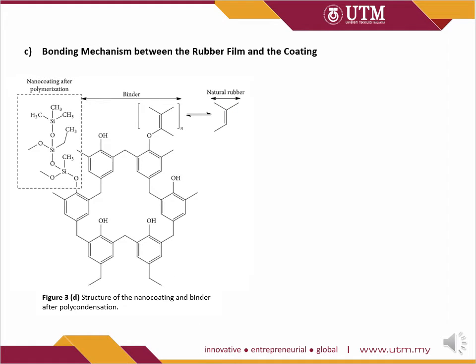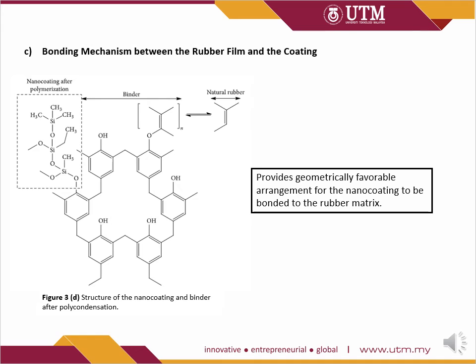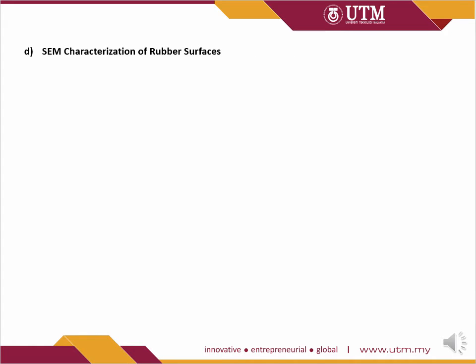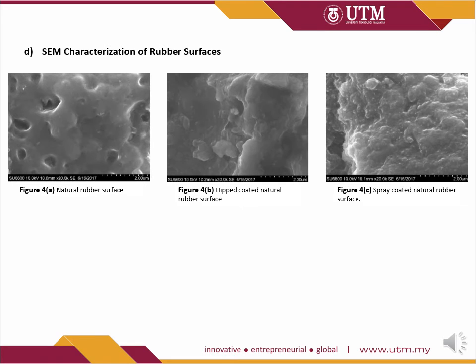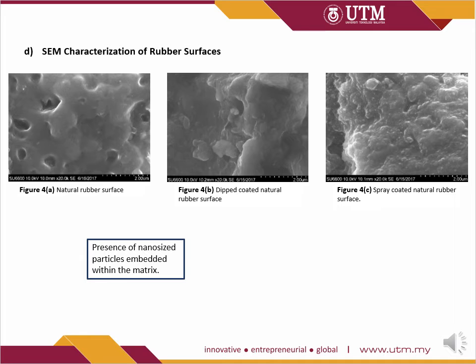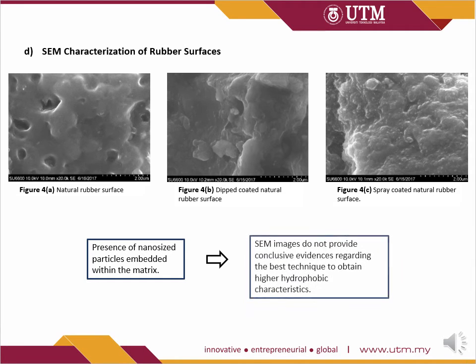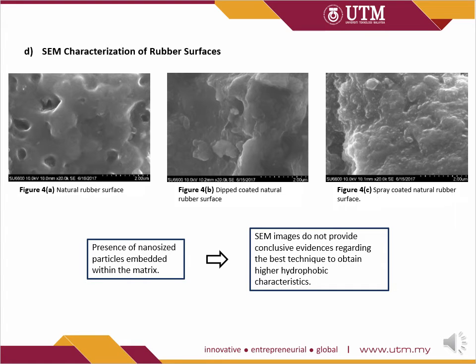Figure 3d shows a possible mechanism for the structure of the nanocoating and binder after polycondensation. The flat orientation of the phenol formaldehyde ring structure provides a geometrically favorable arrangement for the nanocoating to be bonded to the rubber matrix. Next one is the SEM characterization of rubber surface. Based on the figure shown, the surface of the spray-coated glove appears to be rougher than the dip-coated surface due to the presence of nano-sized particles embedded within the matrix. However, SEM images do not provide conclusive evidence regarding the best technique to obtain higher hydrophobic characteristics.